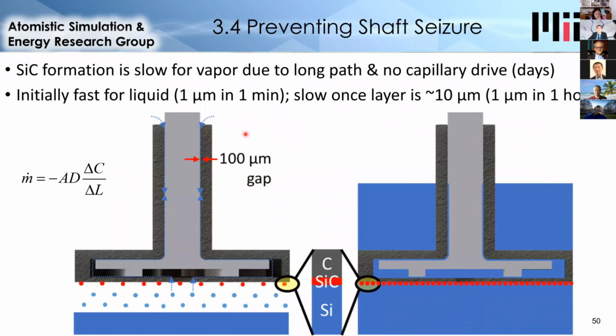So with the full pump system designed, we wanted to try to estimate what would happen when the pump was lowered into the silicon, because we know that this reaction will happen forming silicon carbide. And this is the first time we're putting dynamic components into silicon, which means we need motion between this light gray impeller and the dark gray pump body, but silicon carbide will be forming on both surfaces that are very near each other, and potentially the silicon carbide could cause the two surfaces to bond. And so we're thinking the best we can do is probably to have this layer form slowly.